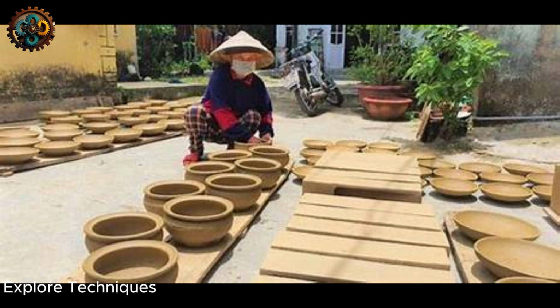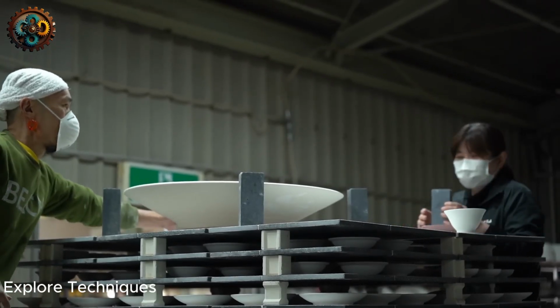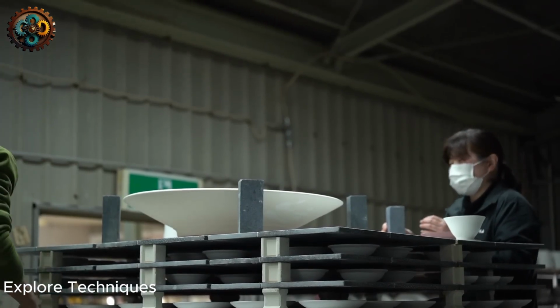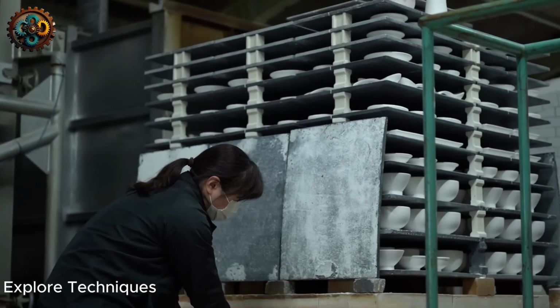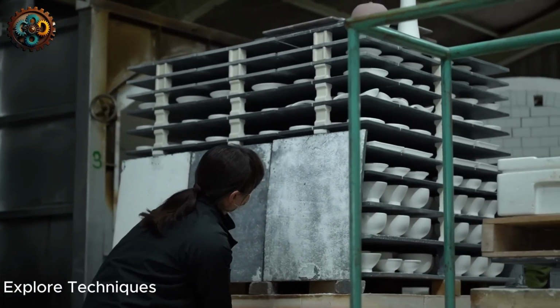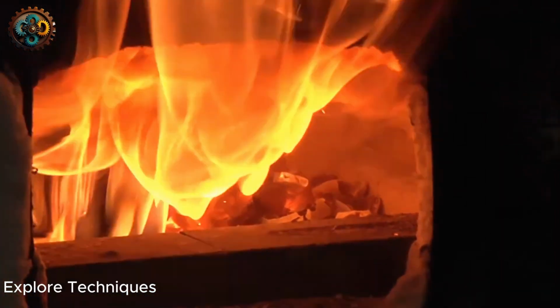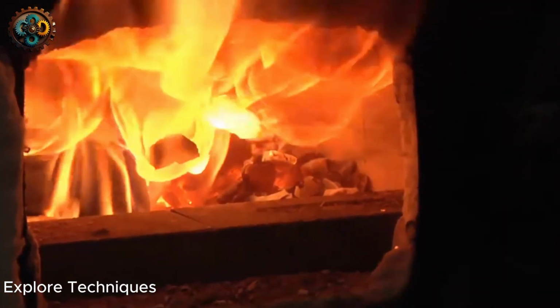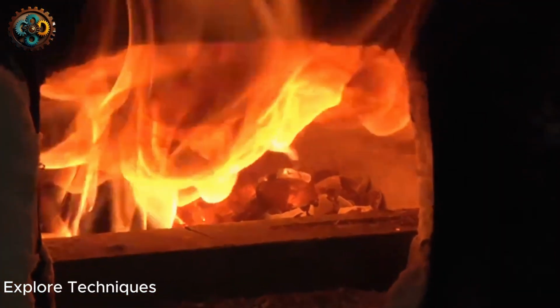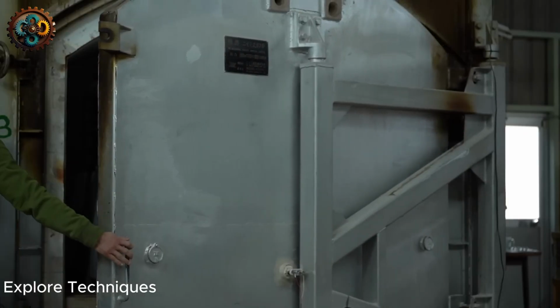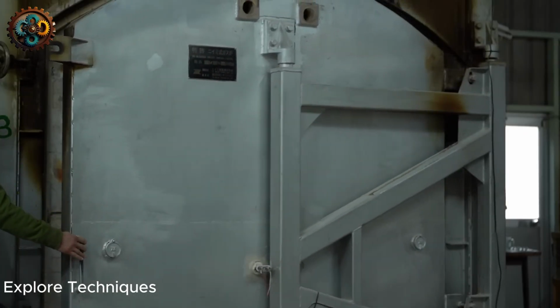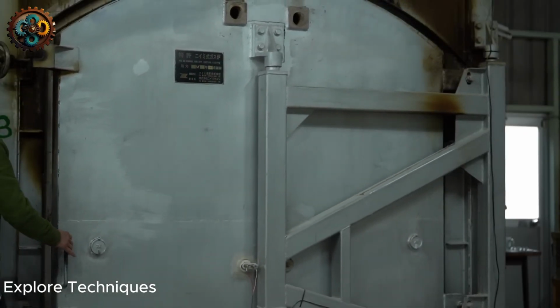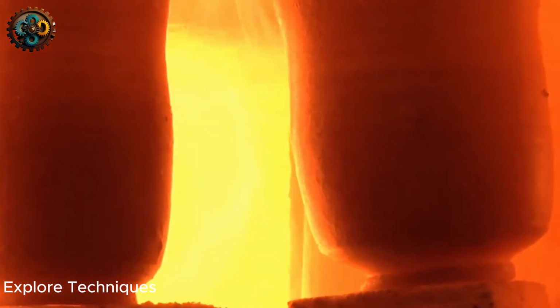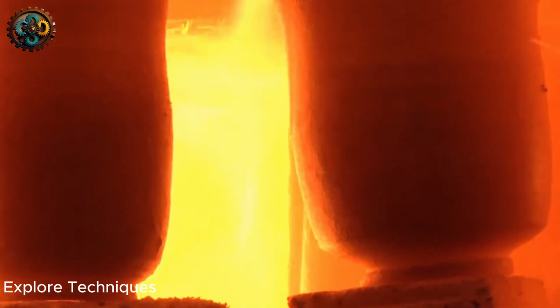The artisan will carefully place the products into the kiln, making sure they do not touch each other to avoid sticking when fired. The firing process lasts from a few hours to a whole day, depending on the type of clay and size of the product. During the firing process, the temperature in the kiln will be strictly controlled to ensure the product is fired evenly and reaches the desired hardness. Artisans need experience and deep knowledge of the kiln to adjust the temperature and firing time accurately.